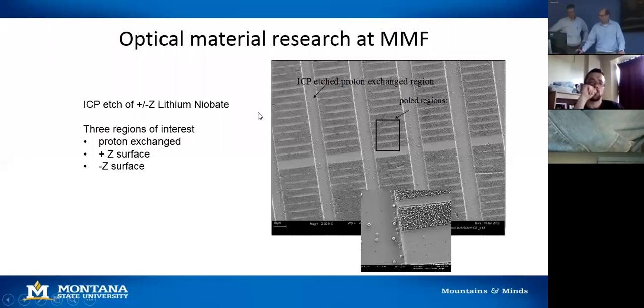One of the most interesting things we just found while we were playing with fabricating ridge waveguides was that it's just chemistry on the etch surface. It was very sensitive to the polarization and also any type of proton exchange where they swap lithium for hydrogen.